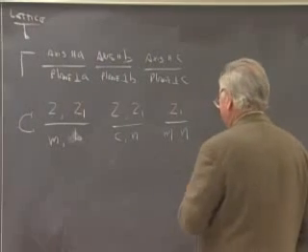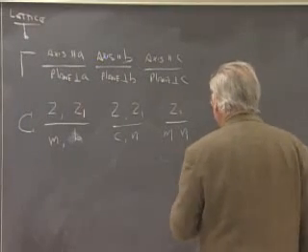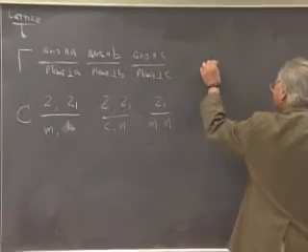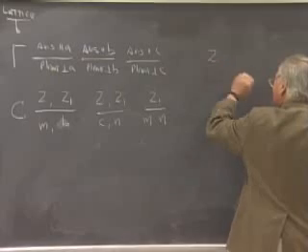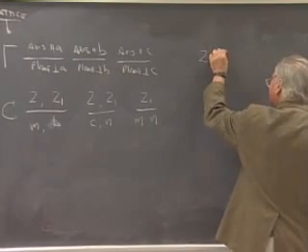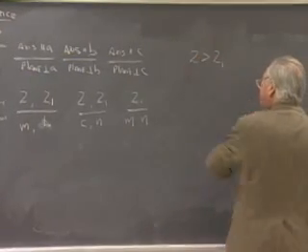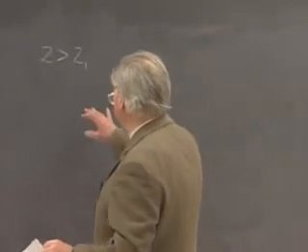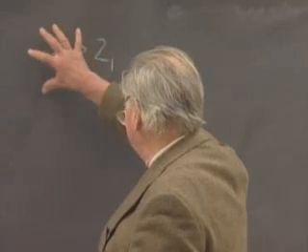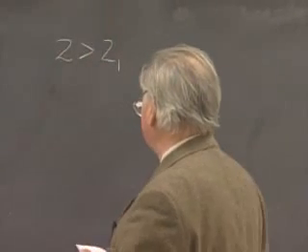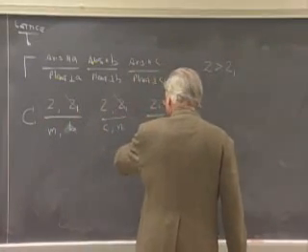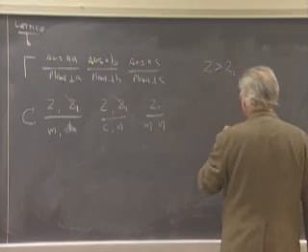All right, so we need a convention. And the convention for establishing a hierarchy of symbols is easy to remember. If you have both a two-fold screw axis and a two-fold axis, the order of preference is that the 2 is chosen in preference to the 2 sub 1 screw symbol. So by this greater than, I mean the preference for choosing it is greater than the symbol to the right. So we get rid of the 2 sub 1 here, we pick the 2, get rid of the 2 sub 1 here, and that stays a 2 sub 1.